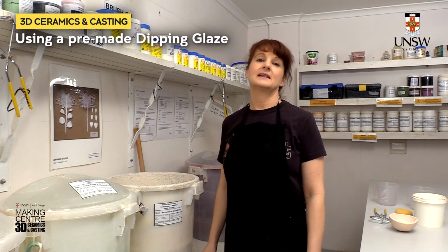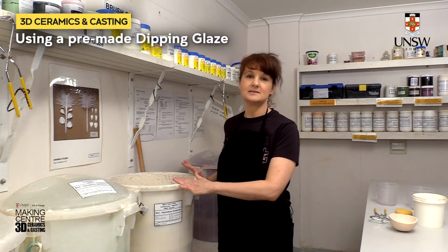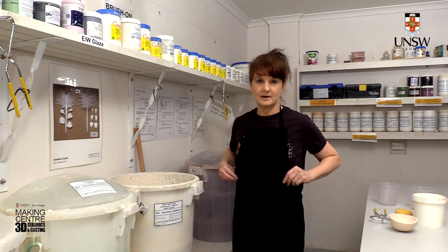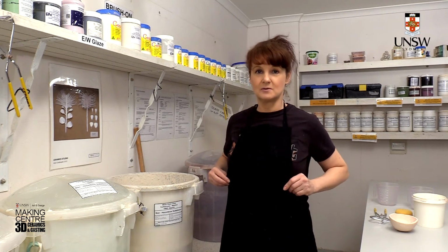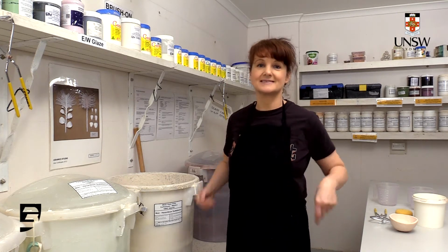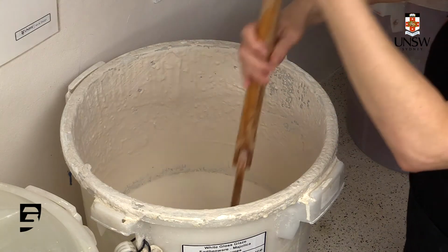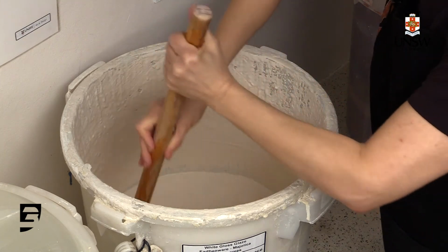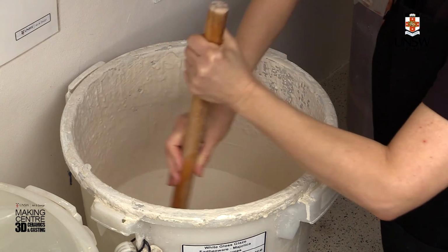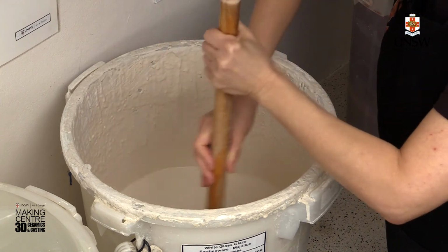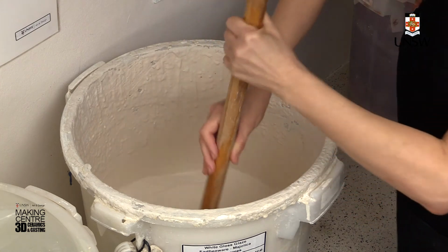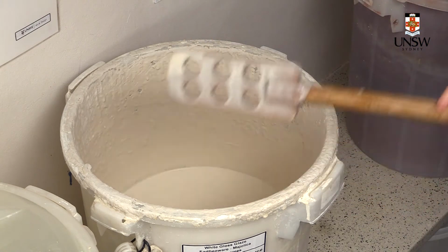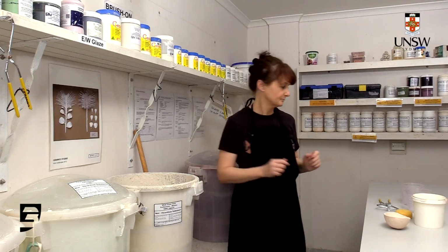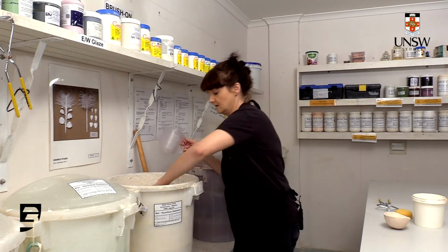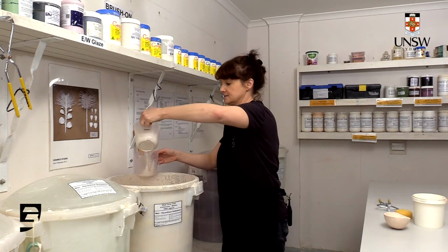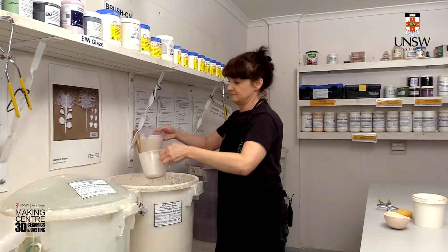I'll now demonstrate how to glaze a ceramic vessel in a pre-made earthenware dipping glaze. I recommend that you wear an apron before you start glazing to protect your clothes from any splashes and silica dust. Firstly, stir your glaze using a stirring stick or a paddle. Make sure you stir the glaze well so the sediment at the bottom of the tub gets mixed through. The ideal consistency of a glaze should be the thickness of light cream.